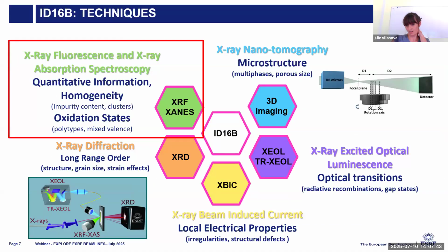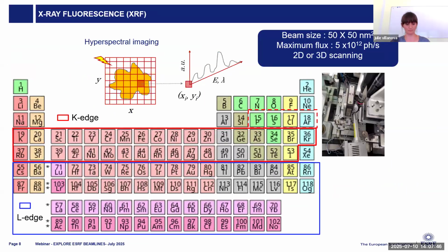I will start with the X-ray fluorescence technique. We use it in a scanning mode, meaning that with this focused beam, we can scan our sample in 2D or in 3D. At each point, we record the full fluorescence signal. That's why we call this technique hyperspectral imaging. Here in the table, you have the different chemical elements that we can map. We can map them using the piezo stage that you see on the right. The beam is coming from the right.